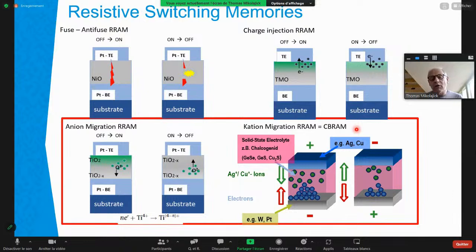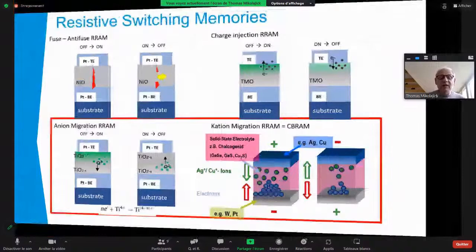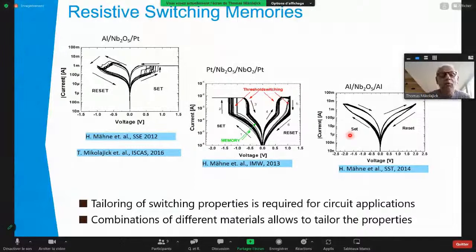electrochemical metallization. Just to give you an idea what you can do with these resistive switching effects, this is from our own work where we work with niobium oxide, and there the beauty is you can change the niobium oxide and interfaces to the electrodes a little bit, and you can tailor the switching characteristics. This is the typical, I would say, digital switching characteristics, as you can see here. Below this value here, not a lot changes, but once you get into switching, the switching is abrupt. In the reset, it's a little more analog, so people that want to use these devices typically try to use the reset for tuning the